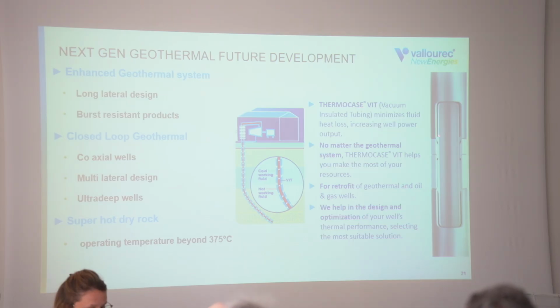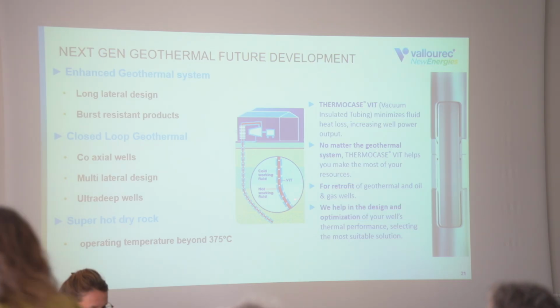So for that purpose, we have not developed but adapted a technology that already existed for oil and gas, which is VIT, vacuum insulated tubing. It's a solution with a pipe-in-pipe technology. In between, you have a vacuum, which prevents the heat of the hot fluid going up in the middle from exiting outside. It works similarly to a bottle for your coffee in the morning. This is manufactured in one of our mills in the US. This technology is now tested in the lab, and we have also increased its temperature rating up to 350 degrees Celsius.